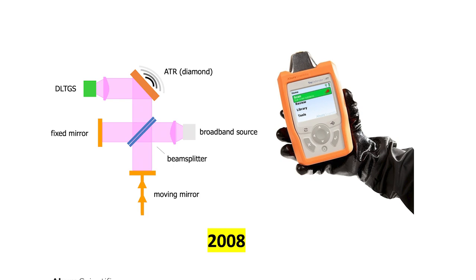It could measure 650 to 4,000 reciprocal centimeters at better than 4 reciprocal centimeter resolution. It had single reflection diamond ATR for point-and-shoot capability and included a zinc selenide beam splitter, and it worked in temperatures from minus 20 Celsius up to plus 40 Celsius.